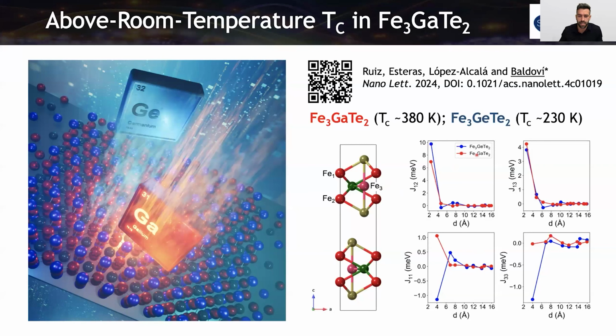So here is the main effect. When we take the J12 and J13, we don't have that much difference. The interactions are very similar. And in these cases, we are taking more neighbors. So this is like J1 to J2, but then to the next J2, and the next, until 16 angstroms. We can observe that they are more or less the same. But when we go to the in plane interactions, in the same plane, so iron 1 with iron 1 or iron 3 with iron 3, we have a drastic difference between the iron gallium, which is ferromagnetic, and the iron germanium, which is antiferromagnetic.